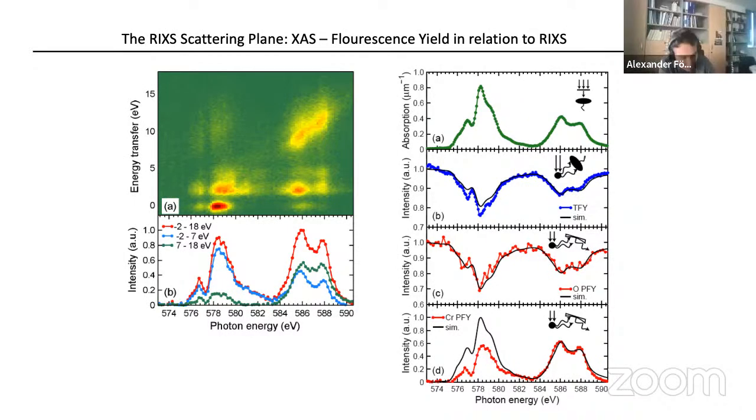You're completely right. I completely agree that in a classical NEXAFS spectrum, 15 to 20 eV above the edge, you already converge into the sudden limit. That is completely normal. In that sense, the surprisingly strong second scattering resonance for water was a huge surprise and is not prototypical. So it continues to be correct. If you just measure a NEXAFS, 15 to 20 eV is completely enough if you want to characterize different oxidation states of iron and this and that, because they truly coincide very rapidly.